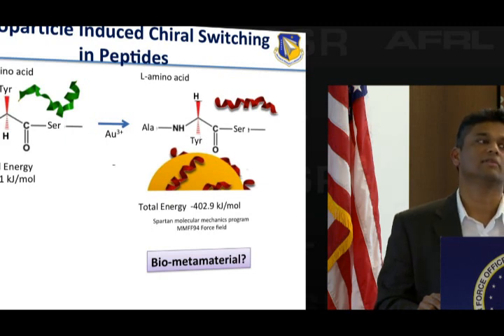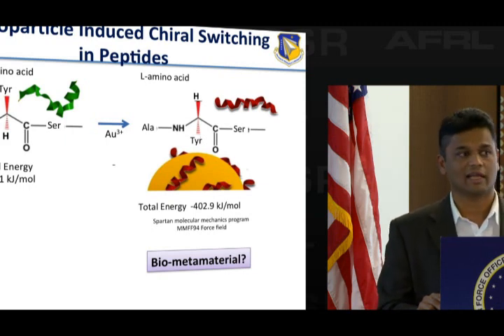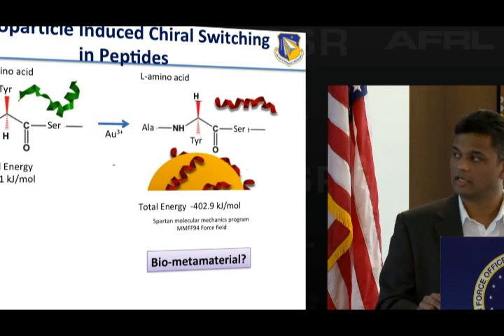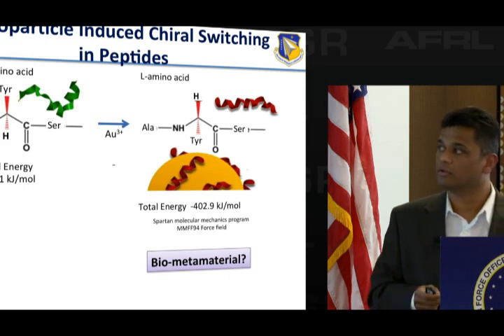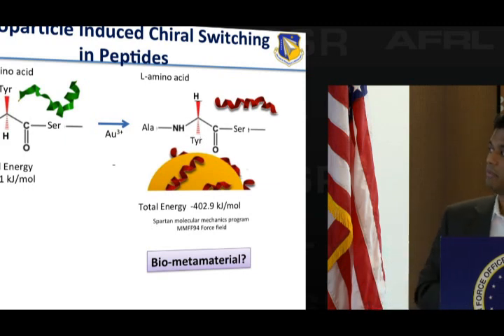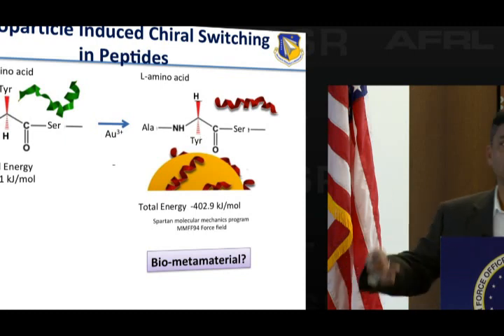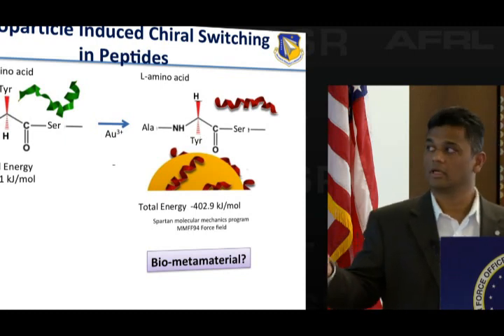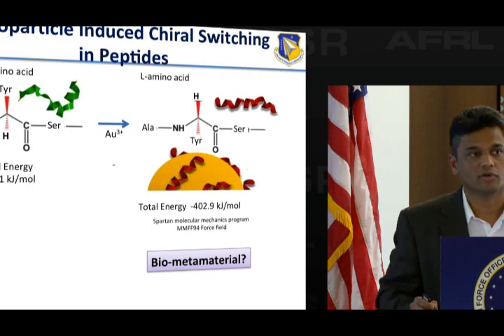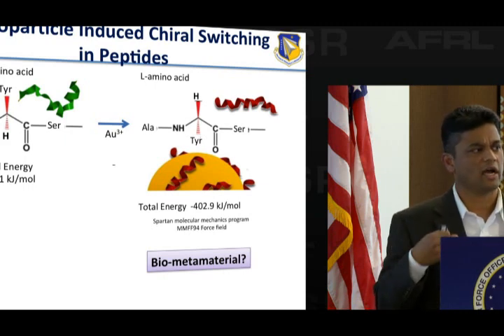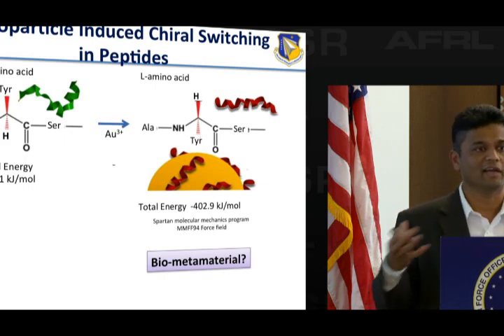So it could be something that's associated with the electronic structure or catalytic activity of some of the structures that drives the bond rearrangement on the surface of the gold nanoparticle. And if you even do some simple molecular mechanics program to look at the energy of interactions between a D amino acid peptide and an L amino acid peptide, the L amino acid peptide always has a higher affinity, has a stronger interaction compared to the D form. So you always ask the question, why has nature selected the L form and never the D form?